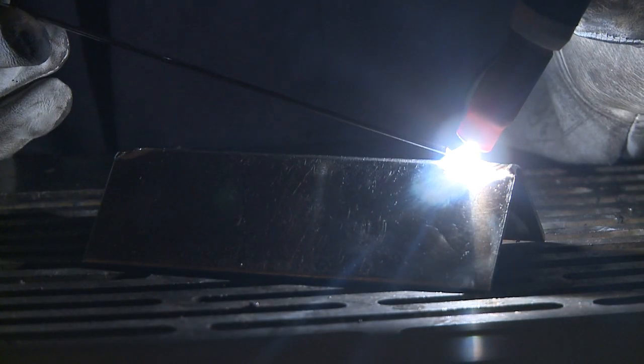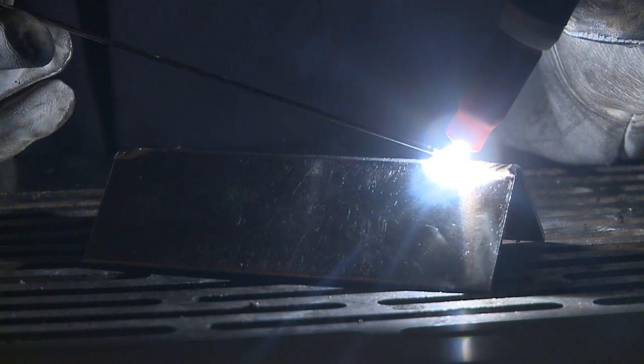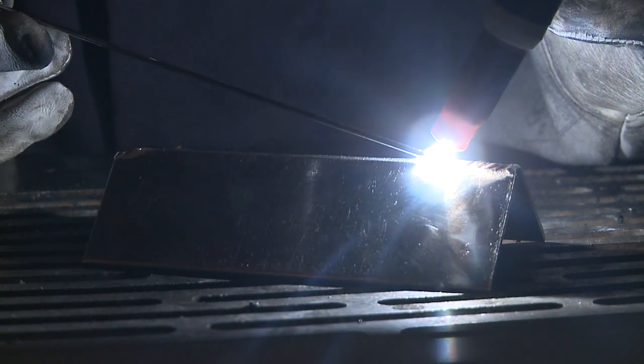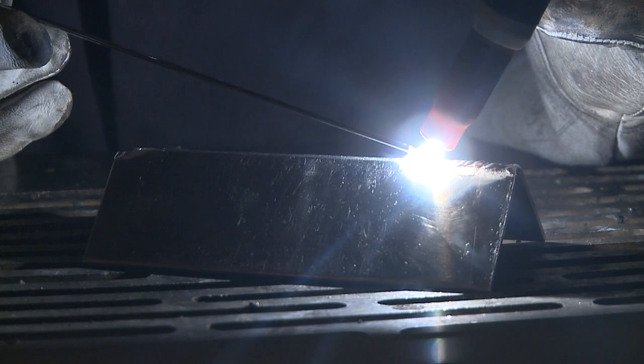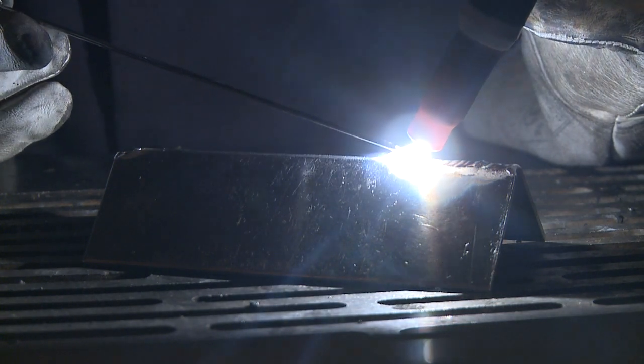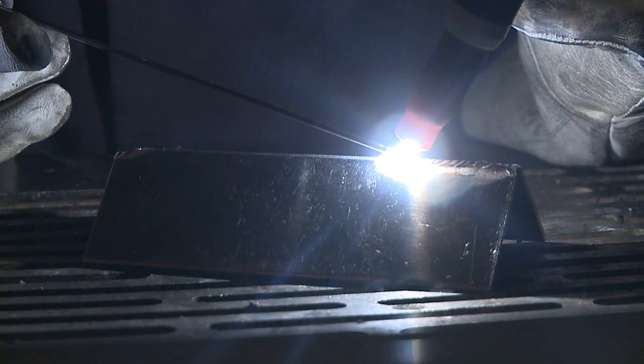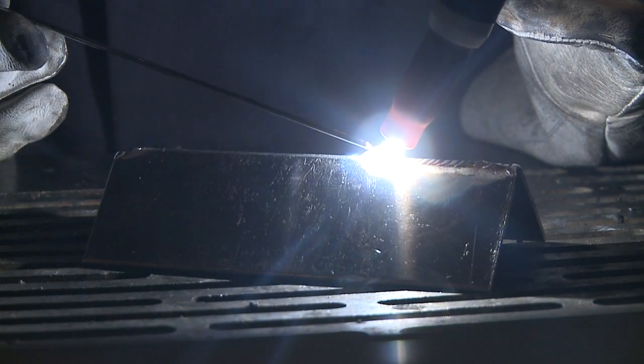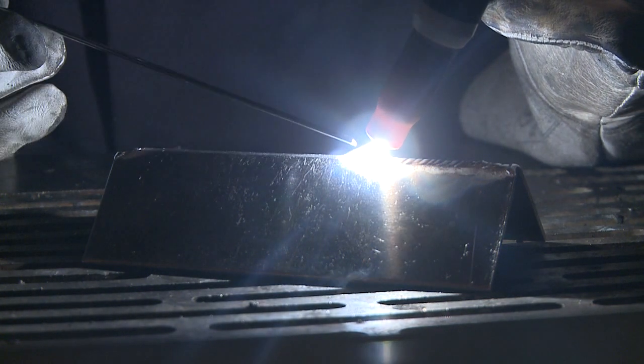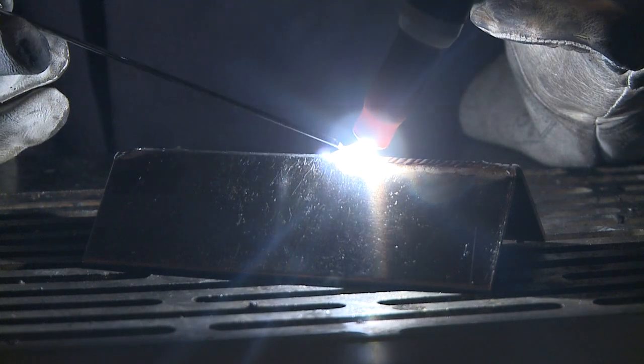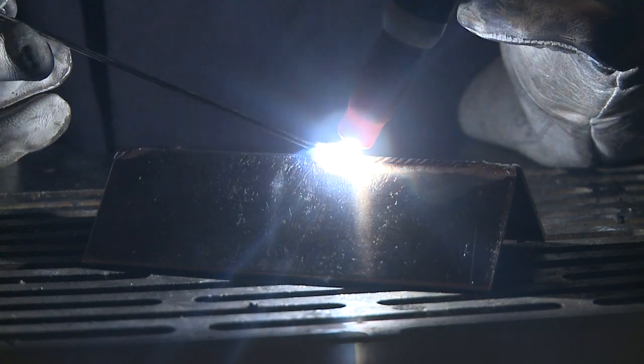As a result, the arc column expands, making the energy less concentrated and spreading over a wider area compared to argon. The more flared out the arc column, the more work surface area has been heated. The heat at the centre of the arc can move more readily downward toward the colder metal at the bottom of the workpiece. This results in a deeper penetrating arc.